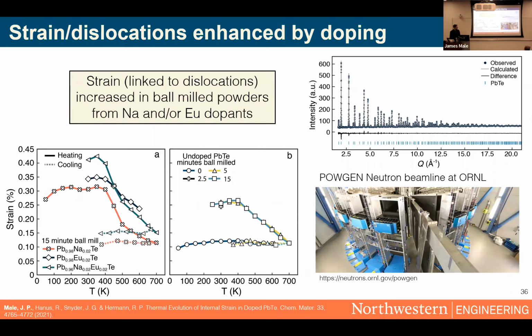And we also found a little more evidence of this in a separate study, which I'm only going to talk about briefly here. But this was a neutron powder diffraction experiment I did with Riley Hannes at Oak Ridge National Lab, where we used the POWGEN neutron powder diffraction beamline to get these really nice diffraction patterns for lead telluride, which we were able to refine to extract some crystallographic strain parameters. So if we just look at the room temperature here for now, on the right here, I'm showing lead telluride without a dopant that was ball milled for varied times. And we actually see this strain that kind of saturates in about 2 minutes of ball milling and doesn't go beyond that up to 15 minutes.